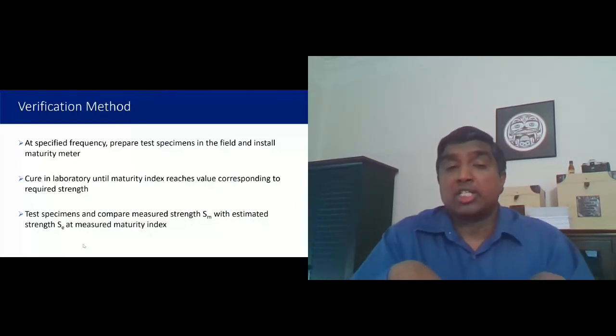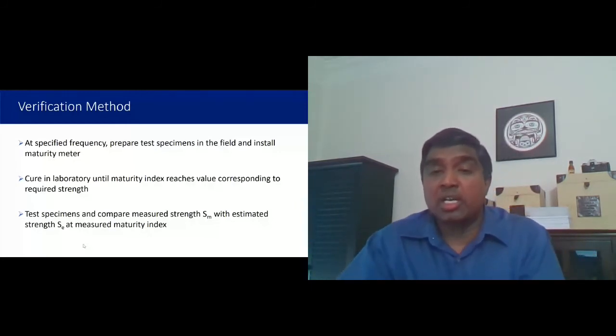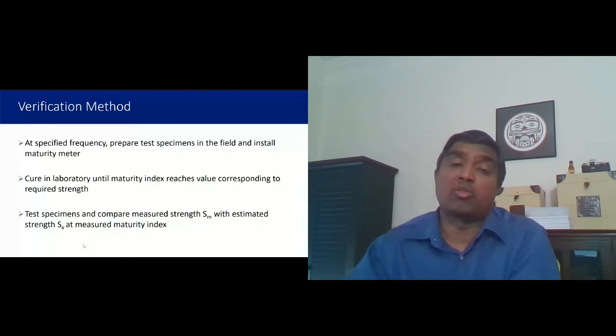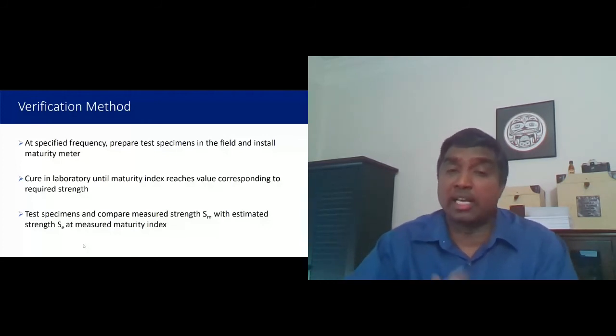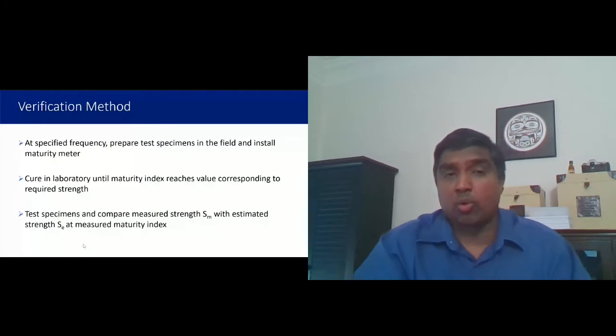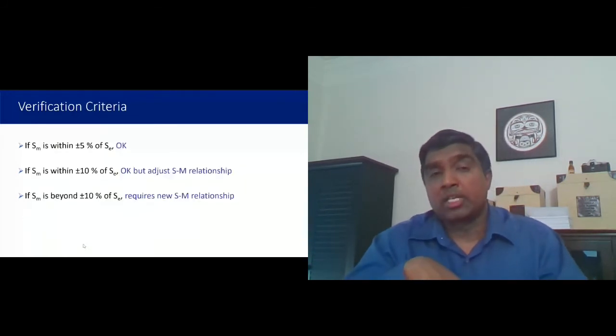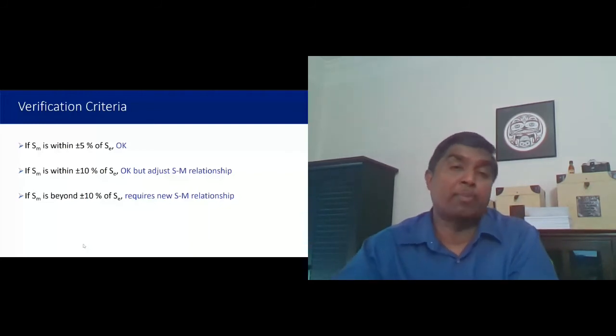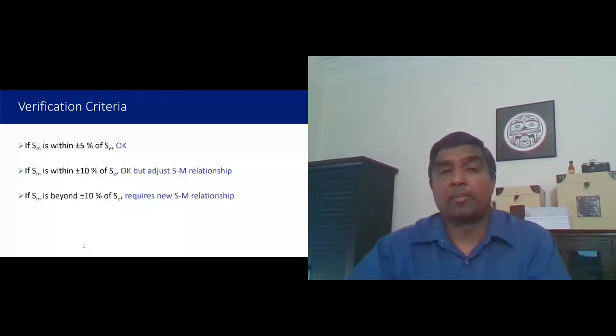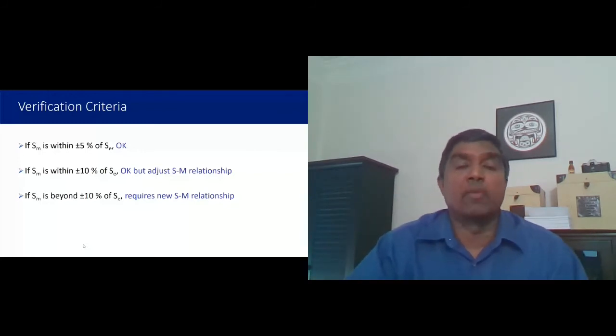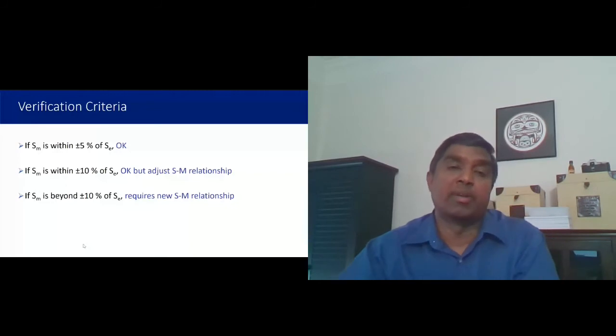Now, if the strength that's measured is closer to the strength that's estimated, then your calibration curve is good. What I mean by that is, if the strength measured from the verification cylinder is within 5% of the estimate given by the calibration curve, then it's okay. We can continue to use the calibration curve.